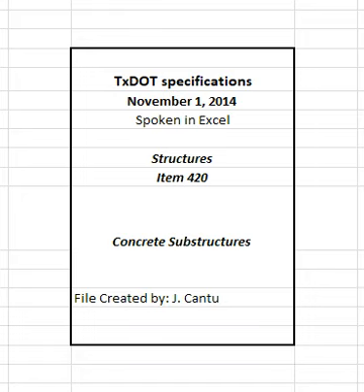defects. Provide burlap material which complies with AASHTO M182, Class 3, 10 ounces per square yard, with the following additions. Manila hemp may also be used to make burlap. Do not use burlap fabricated from bags. Do not use burlap containing any water-soluble ingredient which will retard the setting time of concrete. Provide used burlap complying with the requirements stated above and that has only been used previously for curing concrete. Like new cleanliness is not expected, but contamination with any substance foreign to the concrete curing process, such as grease or oil, will be cause for rejection.